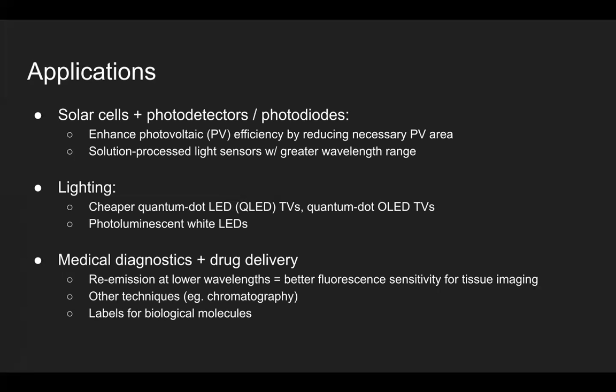Quantum dots have actually already been used for lighting applications. They are used in TVs to take and absorb blue LED light from the TV and re-emit this light at longer wavelengths so that we can obtain red and green light. This makes the TV cheaper because instead of having three different colored LEDs, it allows for one single color to be used, which drops down manufacturing costs. And quantum dots are more efficient than light shutters at turning on and off. And so this allows for better picture quality. There's also work being done with integrating quantum dots into organic LED TVs in order to enhance the already superior properties of organic LEDs and bring further improvement. Quantum dots have already been used in photoluminescent white LEDs, but their stability is not very good and they decay quite quickly. And so more work needs to be done in this arena before we can use them for future generation lighting products.